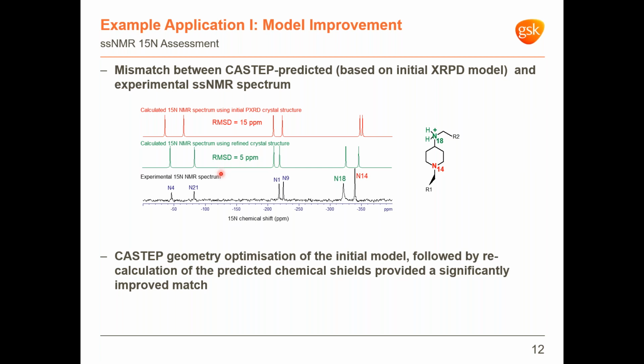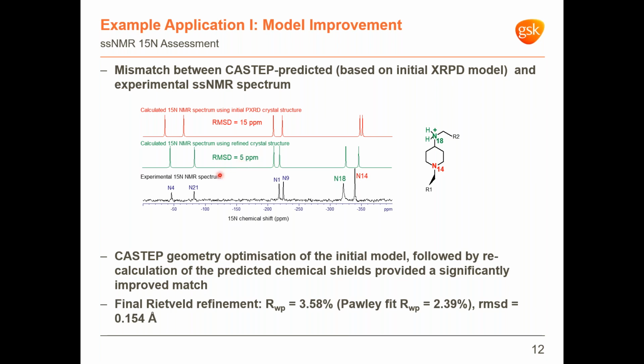Following geometry optimization of the structure in CASTEP, we have recalculated the chemical shieldings on the new structural model and obtained the calculated solid-state NMR trace here reported in green. We can see the improved agreement with experimental data, especially on the signals from nitrogen-14 and nitrogen-18, also accounted for by the much improved overall RMSD. And as mentioned in the previous slide, the final consistency with the XRPD data validates the CASTEP optimized model based on the slightly improved R factor and a rather acceptable RMSD on the refined atomic coordinates.